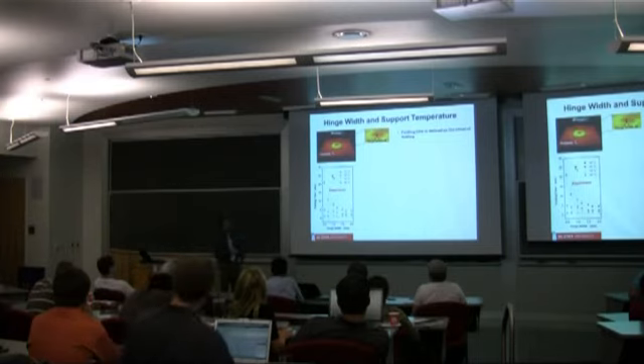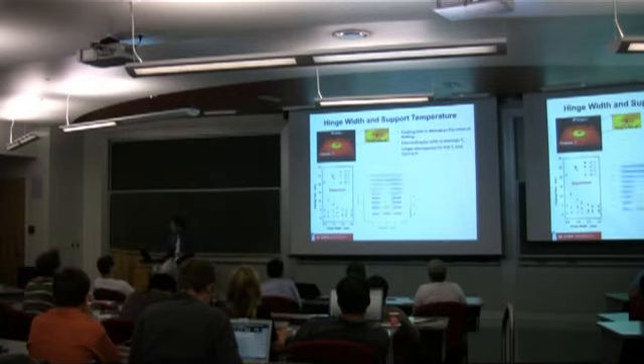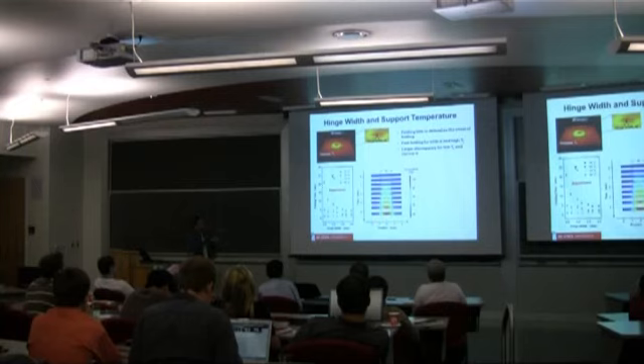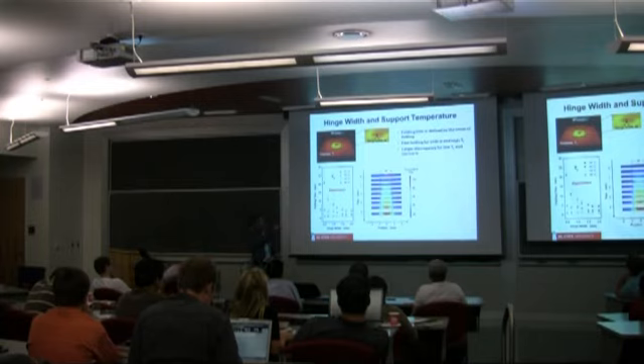So it's very dramatic because you don't have to heat it up as much. We then did a very simple model. And this is a cross-sectional view of the polymer. So you're sort of looking at it this way. And W, again, is the width of the hinge, or the ink.